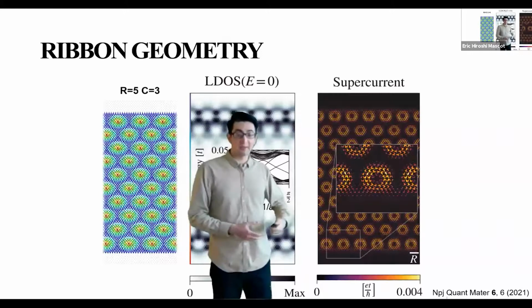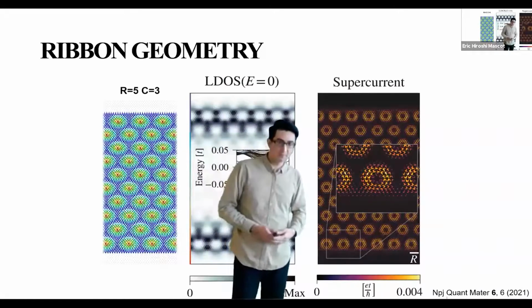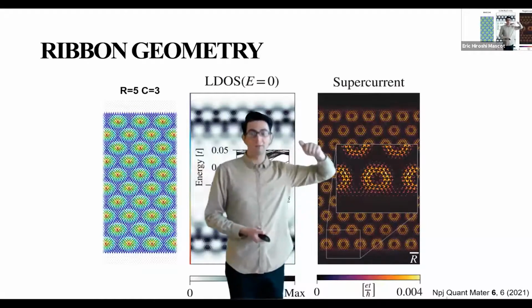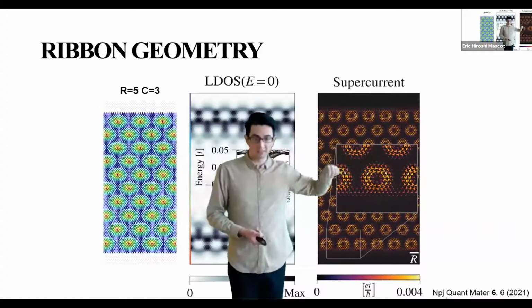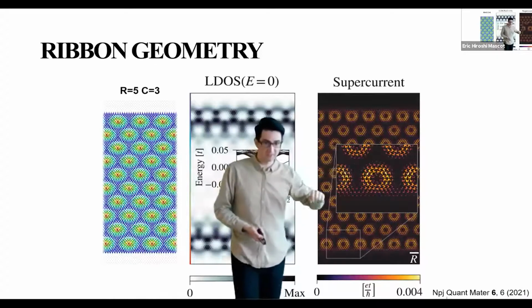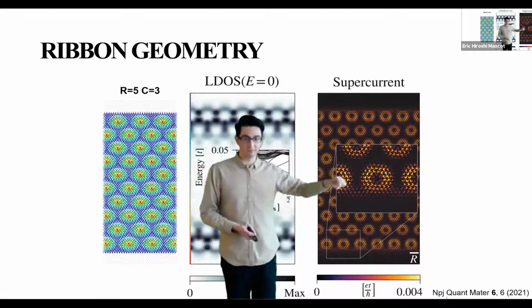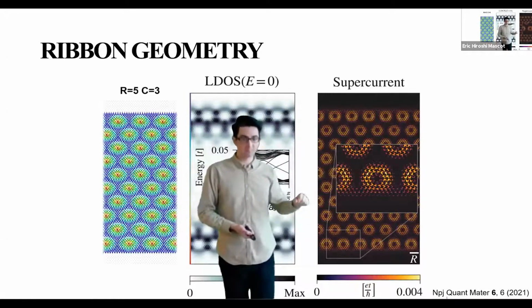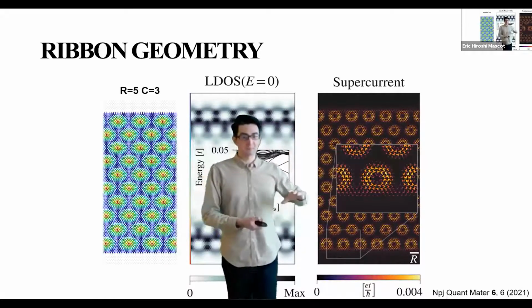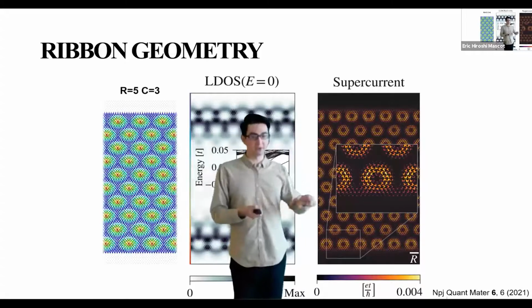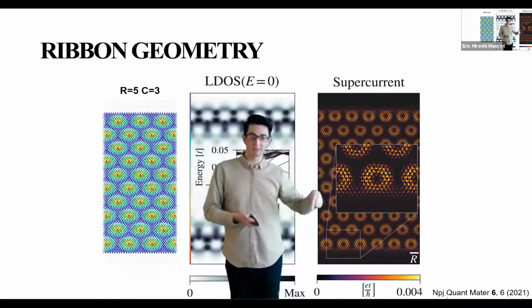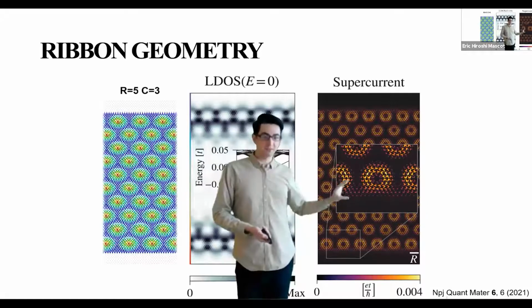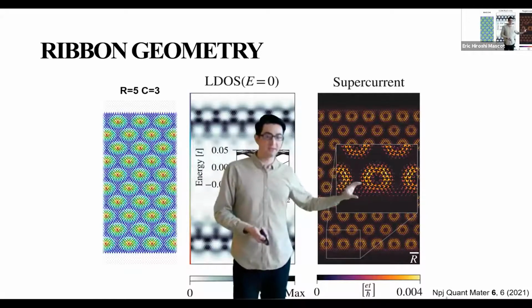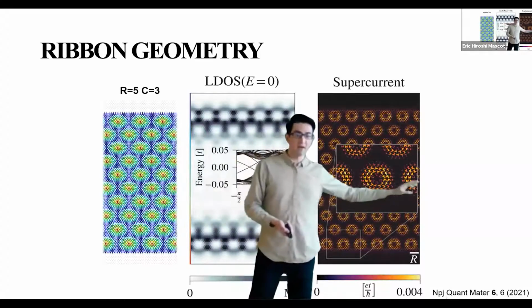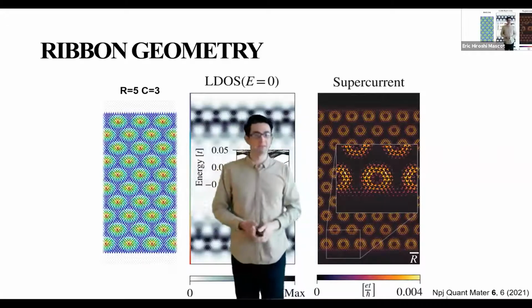And next we calculate the supercurrent. What's interesting is that around the rotating spins, around each skyrmion, you get these persistent supercurrents that orbit around the skyrmions. And so for each skyrmion, you get net zero current because it's just orbiting in a circle. But at the edge, you get a remaining supercurrent that is chiral around the edge of the ribbon.